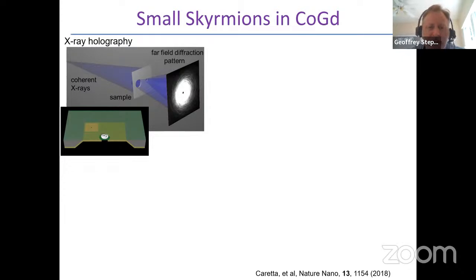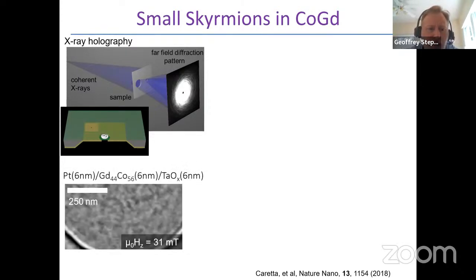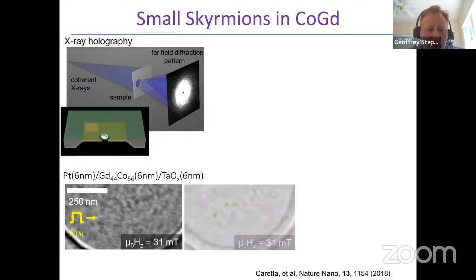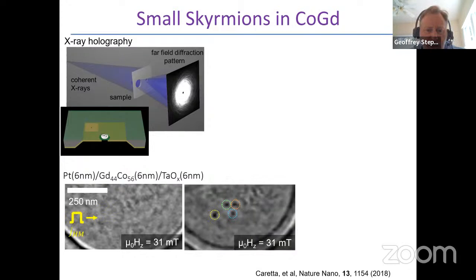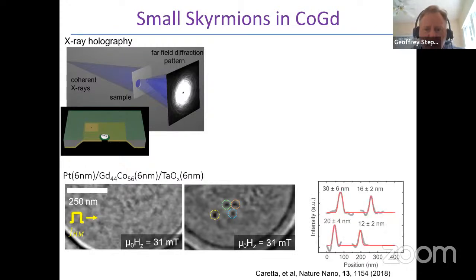to spin ordering, so that even in a compensated material, by looking at one sublattice, you can distinguish the magnetic textures in a material. We were able to, in a tuned cobalt gadolinium film, so in this case, cobalt 56, gadolinium 44, about 6 nanometers thick, again with asymmetric interfaces, stabilize and nucleate with electric current pulses magnetic skyrmions in this material. These skyrmions are stable at room temperature. They are stable at relatively large magnetic fields, and the sizes are on the order of tens of nanometers.